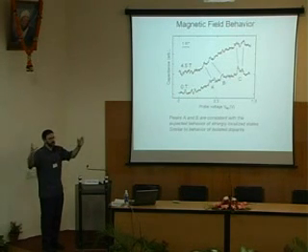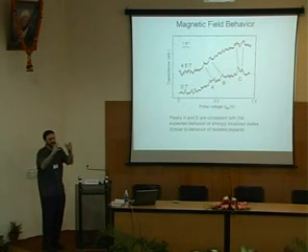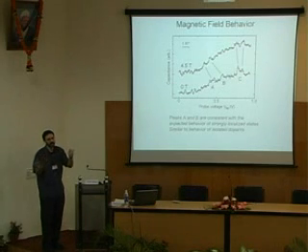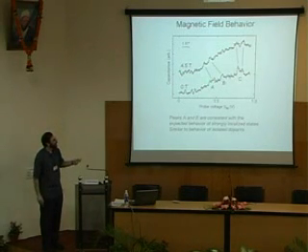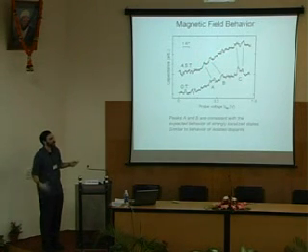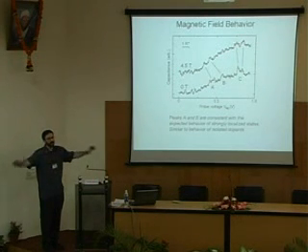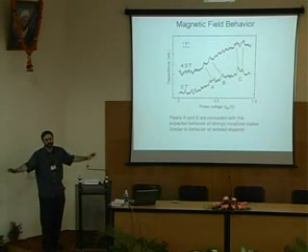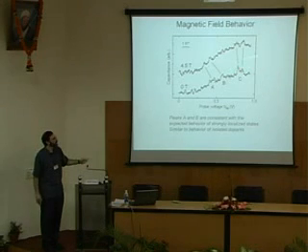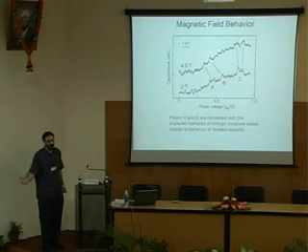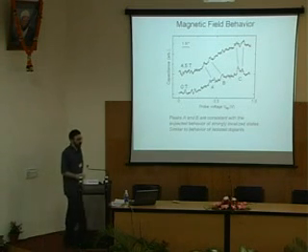On average, this effect that the magnetic field squeezes the electron closer to the proton tends to lower the energy, and we do see that happening. The first 2 electrons do tend to go in at lower energy. And this effect won't work as well for these last electrons. They're more spread out in the first place anyways. They're much more weakly bound in the first place anyways. So it's not surprising that this squeezing effect doesn't do as much. Rather hand-waving way to deal with the data, but at least I wanted to show you that.